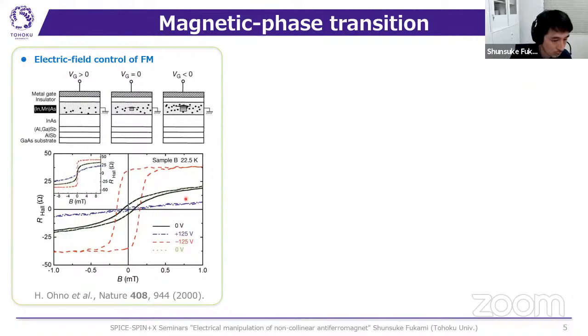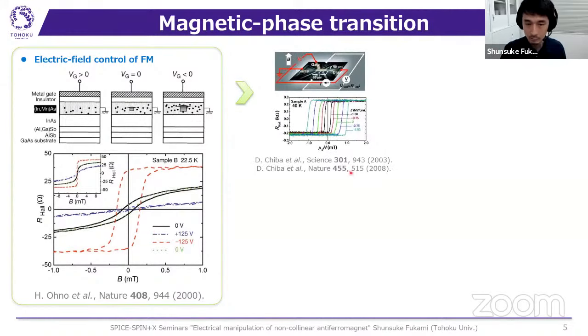And indeed, they applied a negative voltage and induced the ferromagnetism, and by applying a positive voltage, they switched to the paramagnetic state. So the electric field can modulate several magnetic properties. And indeed, a few years later, the same team demonstrated that the electric field can modulate the magnetic anisotropies, and the coercive field was changed by the electric field.